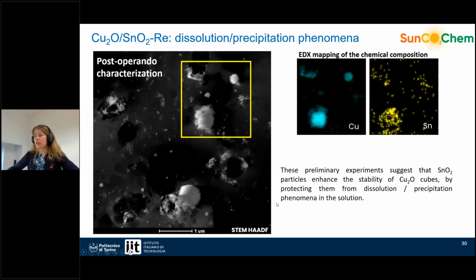This, together with some post-operando characterization, so we did some EDX mapping of the chemical composition, gives us some preliminary information. So basically, it suggests that tin dioxide particles enhance the stability of the cubes by protecting them from the dissolution, precipitation phenomena in the solution. As we can see from this EDX, where the cube was very much dissolved or so affected, there is not much tin there, and the cube that is unaffected is still quite much covered by tin dioxide particles. So I showed you the very preliminary results, and we will be running some more of those experiments and investigate this further.